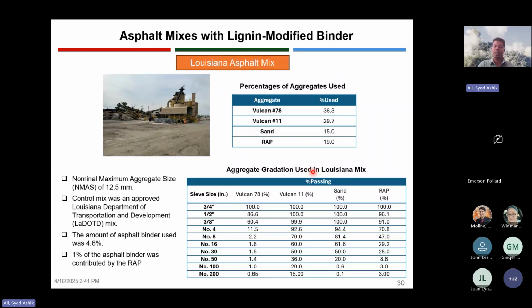So after we got that asphalt binder, LSU wanted to use it to produce an asphalt mix with a nominal maximum aggregate size of 12.5 millimeter. The control mix that they selected was already an approved Louisiana Department of Transportation and Development, LADOTD, asphalt mix. So it was already approved, and it had already been used on the pavement. They used that as a control mix, and they just replaced that asphalt binder with this lignin modified asphalt binder from Louisiana Tech.